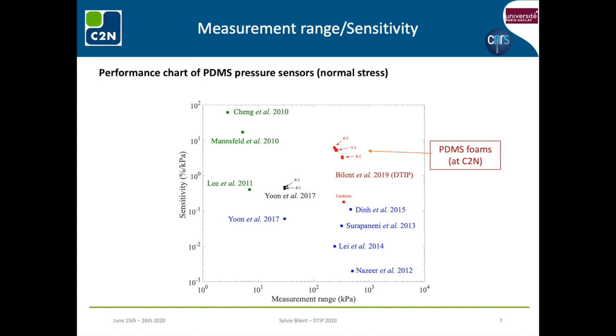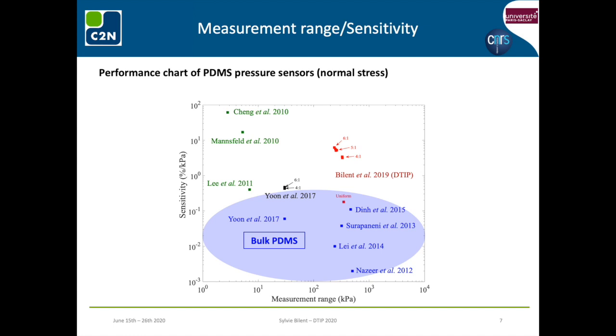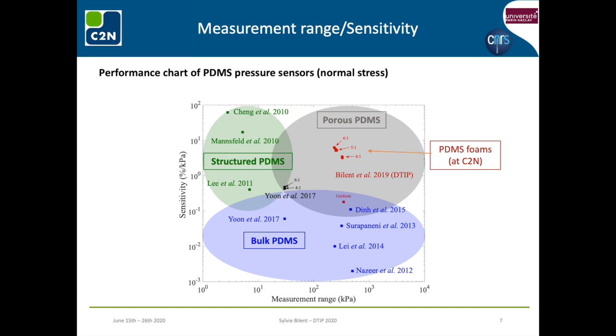Let us represent the performance of pressure sensors in terms of sensitivity expressed in percent of capacitance change per kilopascal and of measurement range expressed in kilopascal in this kind of performance chart. Bulk PDMS-based sensors found in the literature will be essentially located in this blue area, featuring low sensitivity and rather wide measurement range. Structured PDMS sensors are mostly located in this green area featured by a higher sensitivity but a lower measurement range. Early work using porous PDMS film has shown that it's possible to obtain a better trade-off between measurement range and sensitivity. That's why we choose to explore this path and try to optimize this performance.